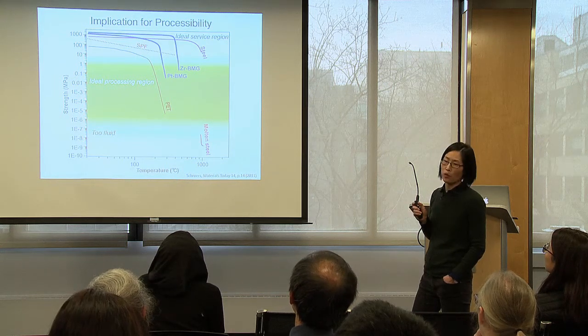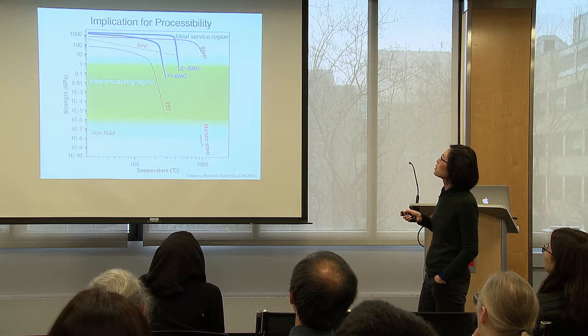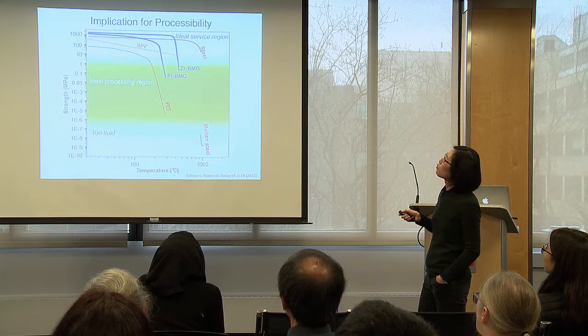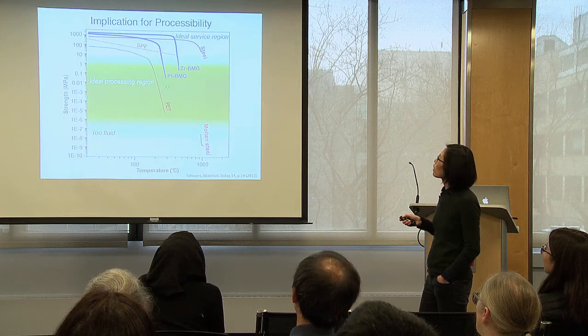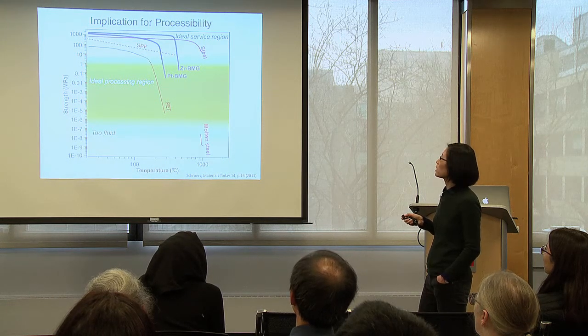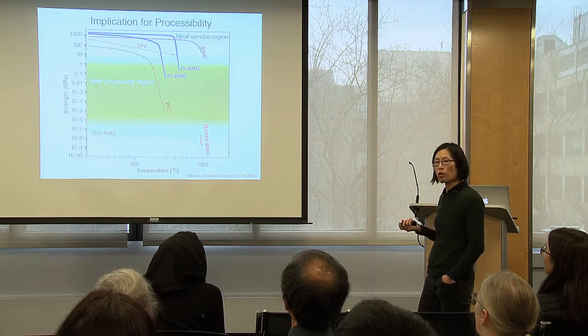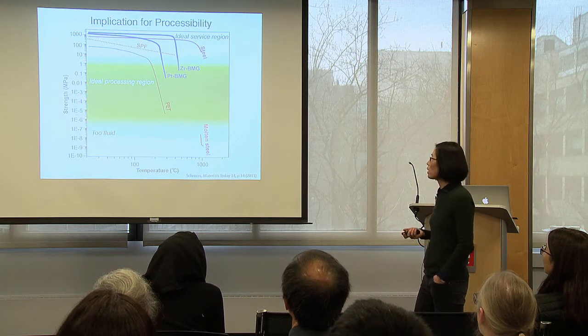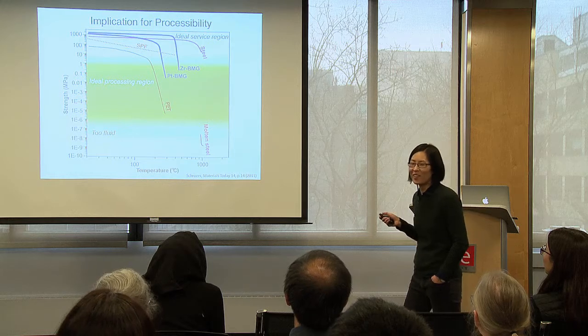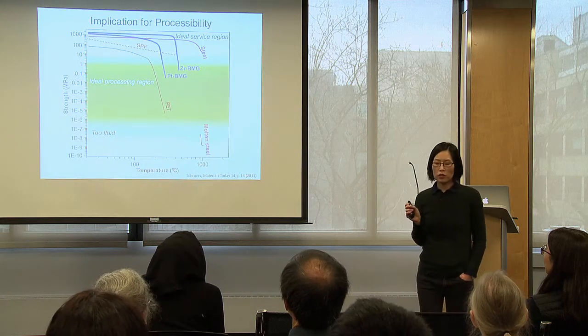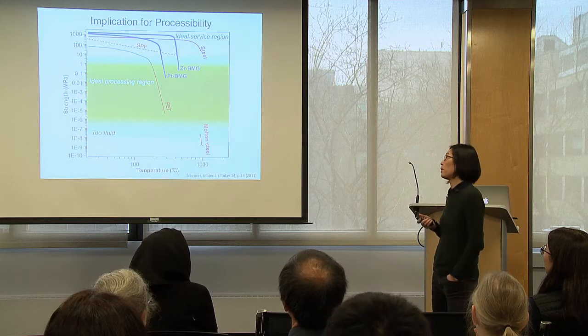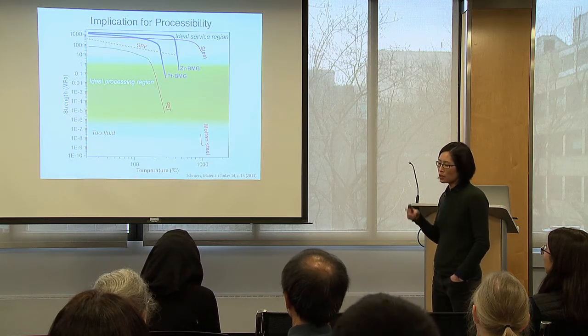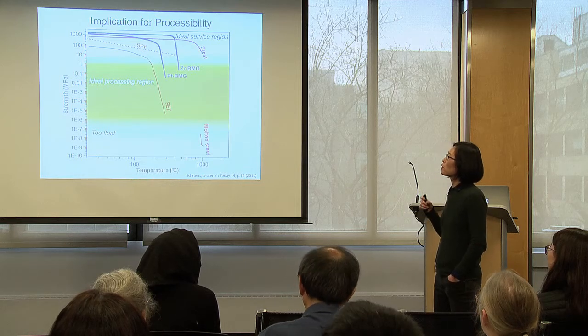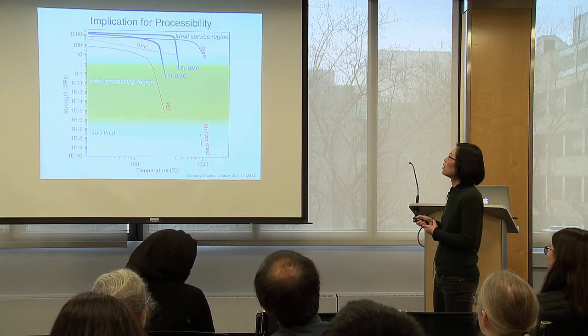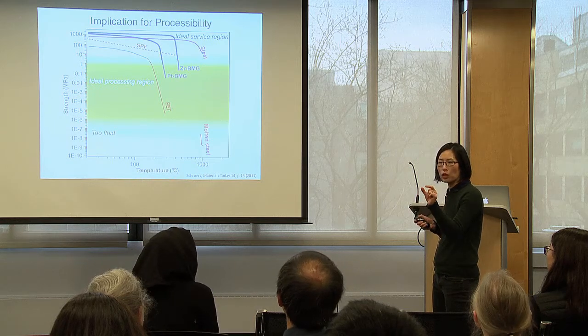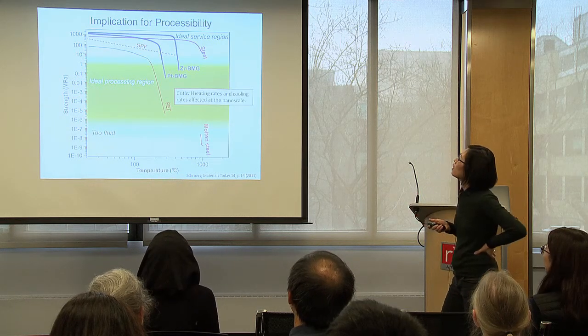Metallic glasses combine both, right? So here are platinum-based and zirconium-based metallic glasses. At room temperature, stronger than steel. You can form them the way you form plastics at moderate temperatures, 200 to 300, 400 degrees Celsius. It's great, okay? The only reason is that this is expensive right now, but it already serves very niche applications very well. So the fact that the crystallization kinetics changes means that for nanoscale structures, you have to know the processing window that you can do this in, okay?